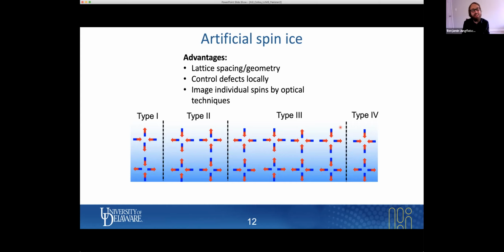So here we have a square artificial spin-ice lattice, and I'm showing all 16 possible configurations. You see that, for example, the type 1 and type 2 states are characterized by a 2-in, 2-out rule. This is the lowest energy state. Then we have high energy states like the type 3 state, which is characterized by 3-in, 1-out, or 1-in, 3-out, or the type 4 state where all spins are pointing inwards or all spins are pointing outwards. So this is essentially something like a double monopole.